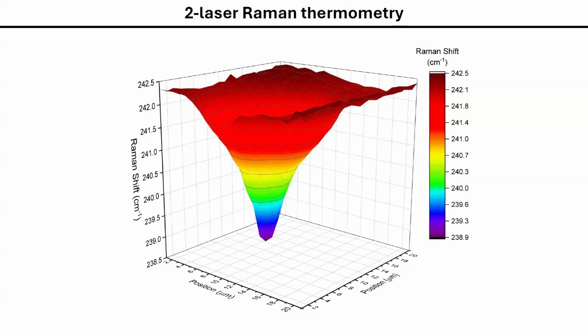Now, in the time-resolved Raman thermometry setup that we also developed complementary to our probe setup, we can only look at the intensity difference between these peaks, and we have less sensitivity to the shifts. First of all, because our lasers are pulsed, and second, because we don't have that much frequency resolution as they have in this big spectrometer. So in our case, we would look at intensity ratios, but in that setup, the most obvious thing to do is to look at shifts of the Raman signal.